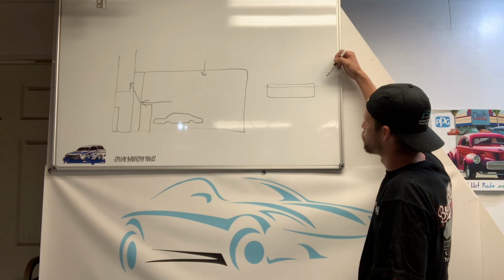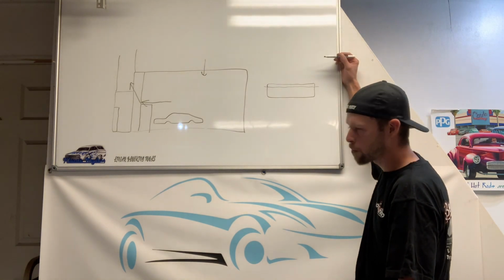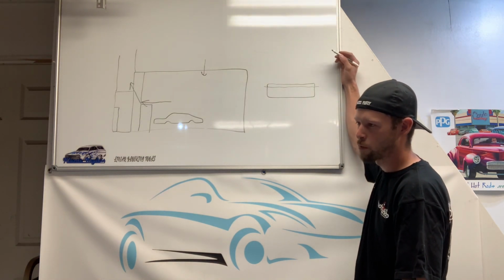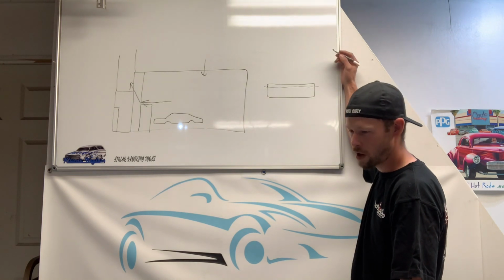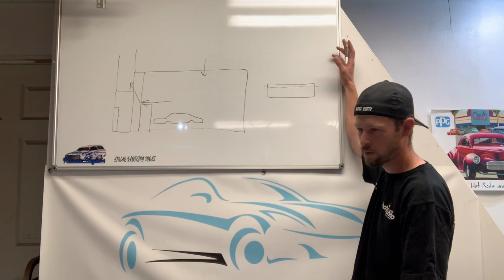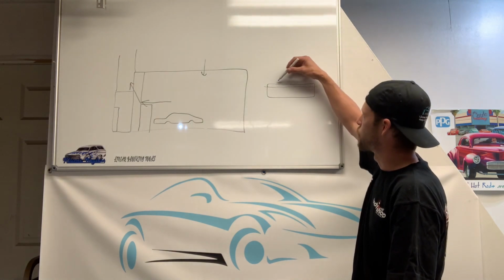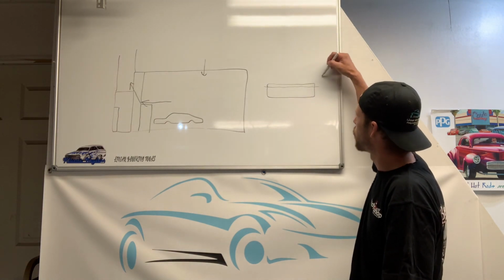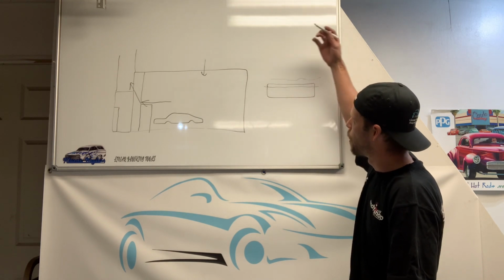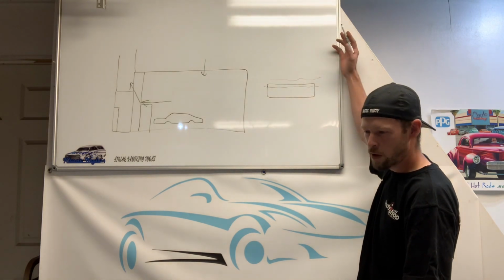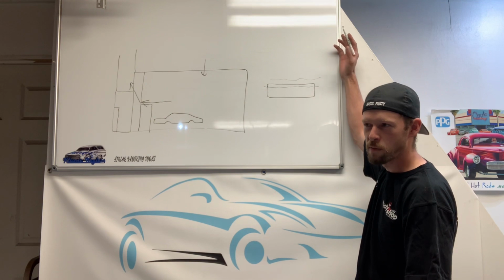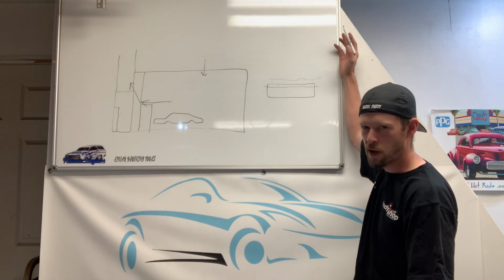The top layer is drying probably because you've got too fast of a reducer in there, and especially in hotter temperatures, if you use a fast reducer and a faster activator, you'll run into this with clear. The top layer has airflow going by it, and we all know that if you add airflow to any equation, it equals faster dry times.